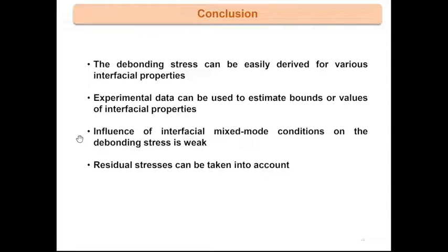With these two parameters, you have the solution for many interfacial parameters. So if you change the interfacial parameters, like in the cohesive zone models, you do not have to re-perform the computations. Okay. You can estimate parameters by fitting experimental data. You can take residual stress into account. You can also take interfacial mixed mode.